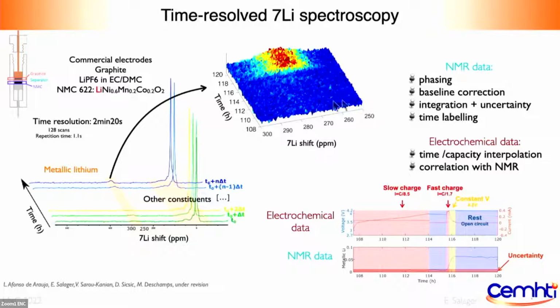Then we had to apply a baseline correction because the positive electrode is very broad, we don't see it, but its redox state changes, and so its effect on the baseline does change, so we need to correct for that also. Then we worked on the integration and also on the uncertainty. We need to time label each spectrum so that we can interpolate it with the different timing grid of the electrochemical data. And then finally, we get the correlation with the NMR. And this is typically what you get.